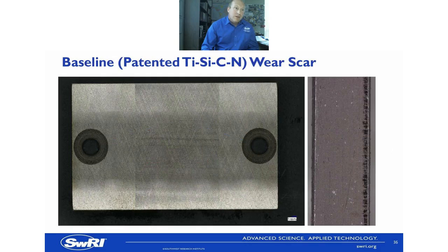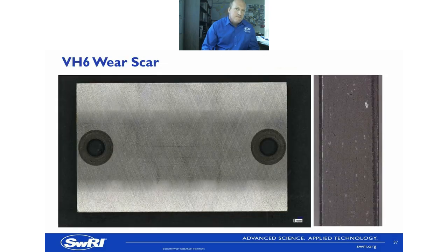So this is the baseline. You can see some of that scoring that I was talking about, where there's lines along the line of reciprocation. And you can see on the ring, there's a little bit of wear on the ring there, just on one edge, which is normal behavior. VH6 wear scar, you have to look a little bit harder to see exactly where that wear scar area is. And the ring's looking very similar to the last one, so no poor effects.